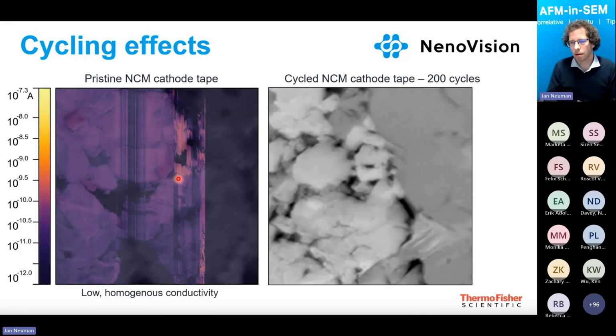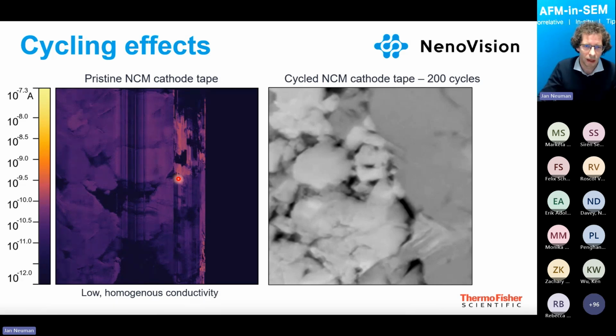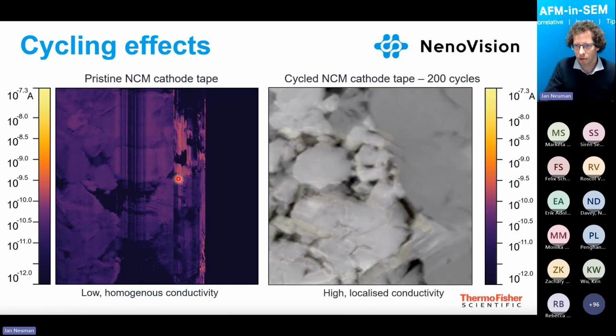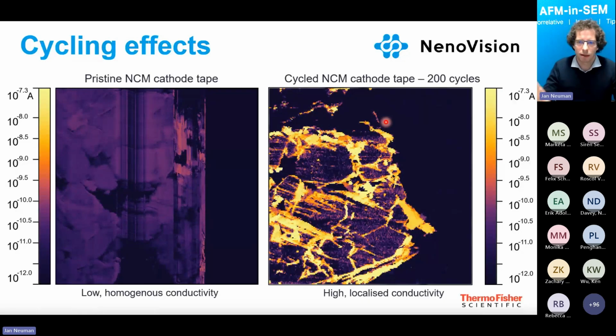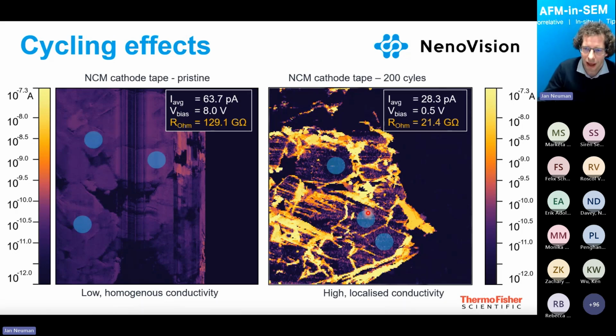And then on both areas, we can measure the conductivity using conductive AFM. This is the conductivity on the pristine NCM cathode, and this is the conductivity after the cycling. No doubt the quality of the images is not the best, not for Nature for sure, but it serves its value because it tells us exactly what we are interested in, which I will show you. Directly, we can see very bright spots, which are an increase of the conductivity. In the first stage, I will not focus on that. We'll focus on analyzing the changes of the average conductivity on the cathode materials, which you can see here. We averaged it, and what we can clearly state is that the resistivity drops significantly from 130 gigaohms in the pristine stage to about 21 gigaohms after 200 cycles.